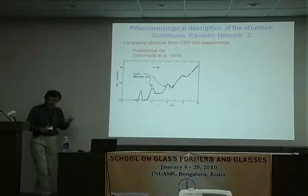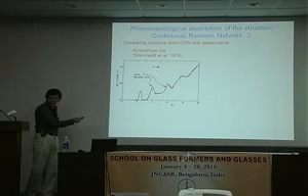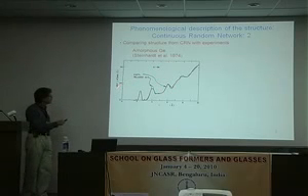Now, surprisingly, this approach works quite well. So this is old data, 30 years or more, where, you cannot read it, this is amorphous germanium, okay? And so this is just a 1-component system, which you can generate in an amorphous form. And here, this is the radial distribution function as a function of the distance. And the experiment is the dashed line here. So here it's coinciding. Here you see a small difference, and here as well.